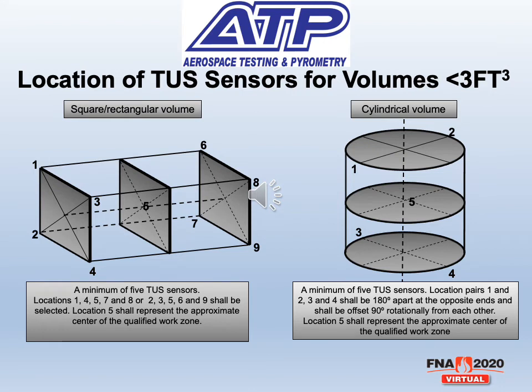So in this instance, if you're choosing your 4 corners here and you want to choose locations 1 and 4, that's acceptable. Then you would have to use locations 7 and 8 in the back of the furnace, which are opposite corners from the front zone, and then again 5 in the center. For a cylindrical furnace that is less than 3 cubic feet, you'd have your top thermocouples 180 degrees apart from each other, and the bottom thermocouples 180 degrees apart from each other, but those would be 90 degrees perpendicular to the top of the furnace, again 5 in the center. This gives us a better look at what the furnace is doing from front to back and top to bottom in these locations.